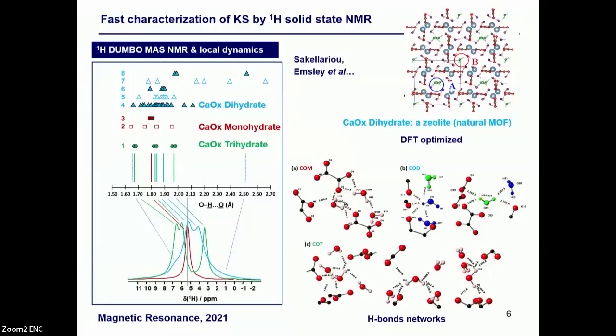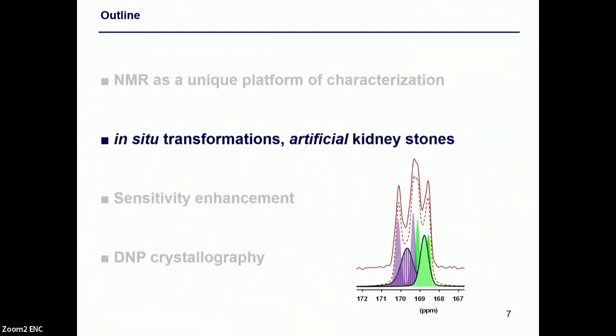And if it's not rigid, you can allow flipping of a water molecule, so you introduce dynamics, and then it's possible to completely interpret the chemical shifts, the isotropic chemical shifts obtained for the three phases. So now I switch to the second part, dealing with in situ transformation.